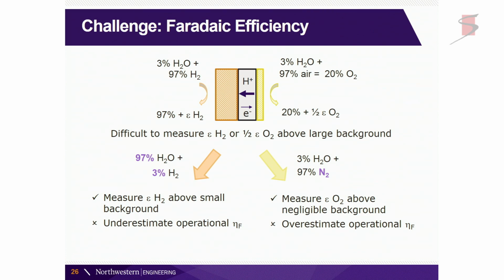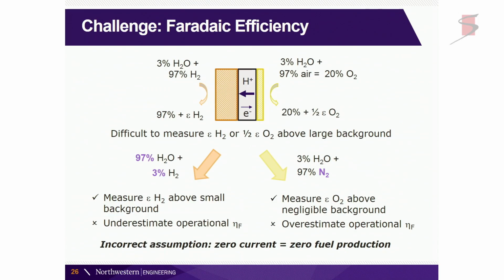So that is inherently a challenge, and I can say that when we looked at the literature to try to compare our numbers, I'm pretty sure that everyone's done this wrong. Not that many people have measured it. Most people would just assume that because this is an oxide electrolyte, this is 100% Faradaic efficiency, there's really nothing else that can happen. But that small percent of electronic conductivity is probably not a big deal, but in fact it is a big deal.